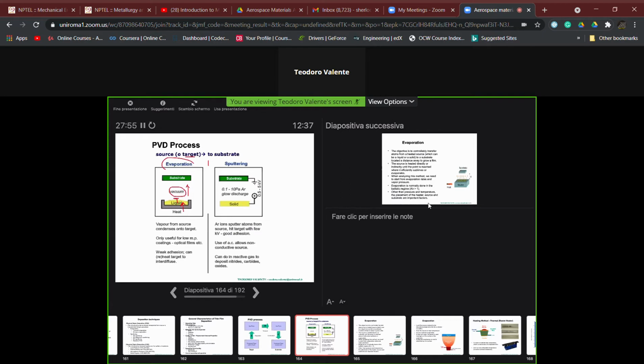the least expensive, but it has a limitation, because obviously it is possible, in order to achieve suitable deposition rates and suitable performance of the process, only with low melting point materials used for coatings, like, for example, optical films. Then we have nothing inside, just evaporation and condensation, and so generally we also have a weak adhesion of the coating on the substrate, but it can be useful for some kinds of applications. Sometimes, in order to reinforce the adhesion between the coating and the substrate, a post-thermal treatment, that is a reheating to let interdiffusion happen, is made at industrial level.